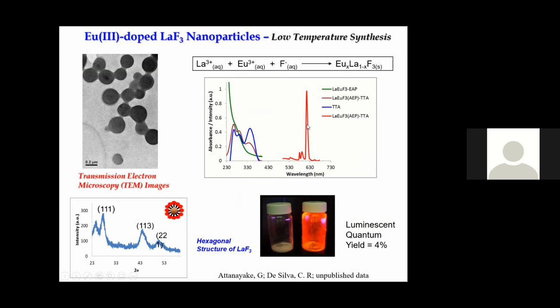So that means we have proved that you can make a nanoparticle, coat it with the organic ligand, and it will do the Förster type energy transfer, or FRET. This left figure shows without that coating, the right figure shows with the coating. You see that it emits light. And our efficiency is not that great. It's 4%. We still can see it, but it's not that good.